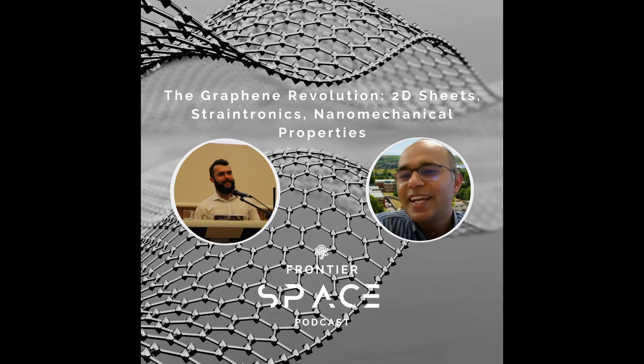So these wrinkles introduce this semiconducting behavior, because fundamentally, the Dirac cones of the graphene are touching, let's say the band gaps are touching each other. But if there are some defects, depending on the density of the defects, this band gap changes. So the semi-metallic nature of the graphene transforms into semiconducting nature. So that's one beauty of the wrinkles. Of course, mechanical integrity will be compromised. You will not get a steel-like material, but in electronics, you do not need it. You do not need armor in the electronics industry. So here the electrical properties are sufficient.